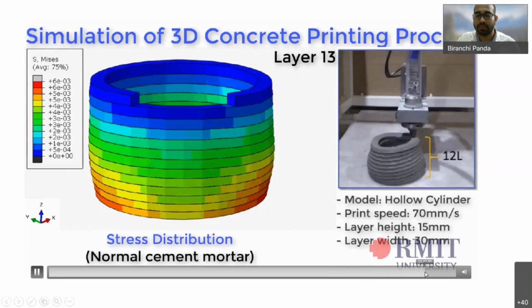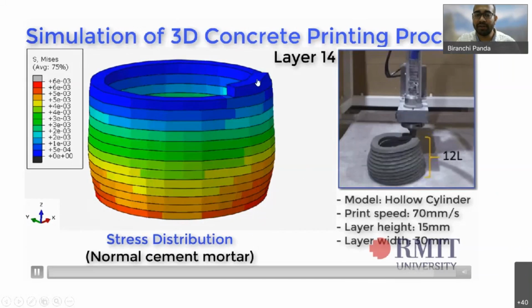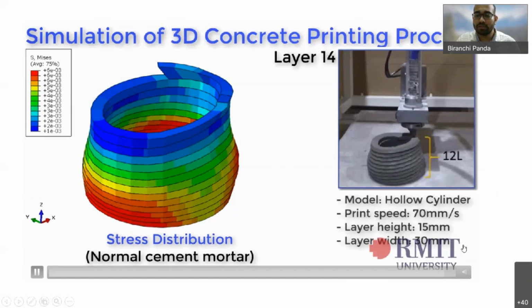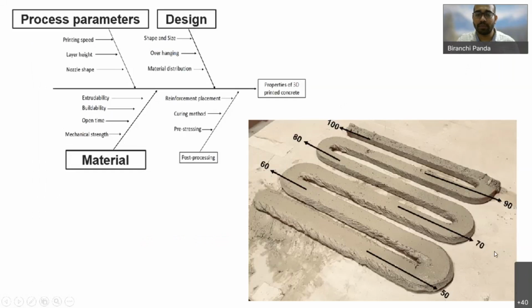So the bulging effect you can see. Why is it important? Because sometimes we want to print a very tall structure, so we can't directly go on a trial and error basis because it's a very large structure. If it fails in between, it's a very difficult task to clean all the materials and reprint. So it is always better, with our experience and with material data, to use this buildability model so that you can predict at which layer it is going to collapse.